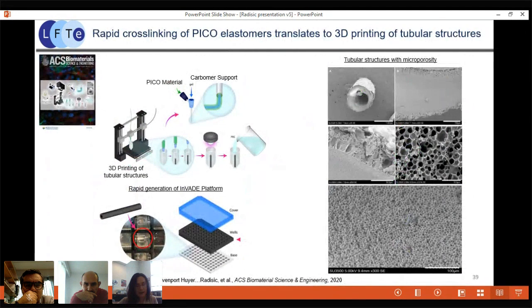Because PICO elastomers cross-link much faster than our other elastomers, including those like POMAC or elastomers based on 1,2,4-butane carboxylic acid, Human, who is the organizer of this seminar series, was able to use these PICO elastomers in a 3D printing application. So using extrusion printers, and if you use a coaxial print head with the carbomer as a sacrificial layer, Human was able to really rapidly print these tubular structures and use them to create some of our organ-on-a-chip platforms. In the other body of work from our lab, these organ-on-a-chip platforms are all created by 3D stamping, which is more laborious than the 3D printing procedure that Human developed here. So you can see these tubes that he's able to 3D print, and they do have a good level of microporosity that really increases the permeability of these materials.